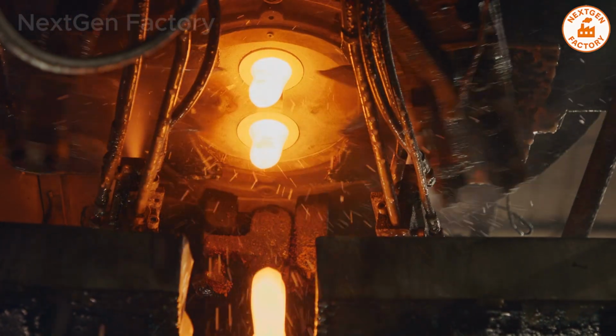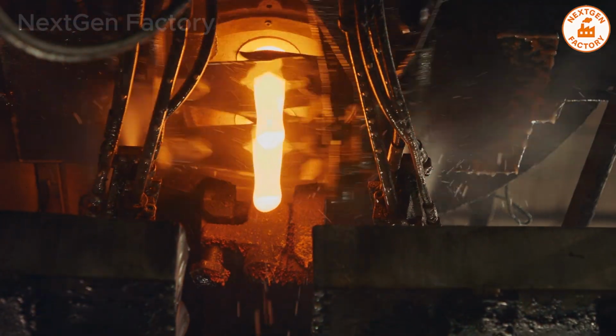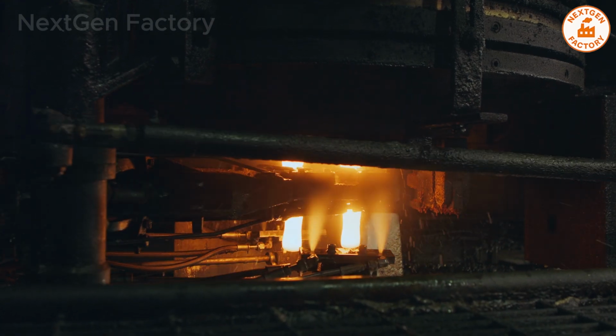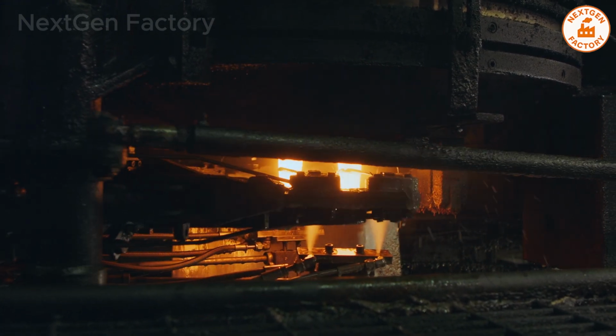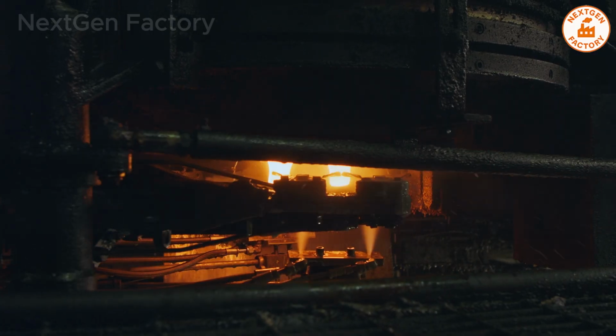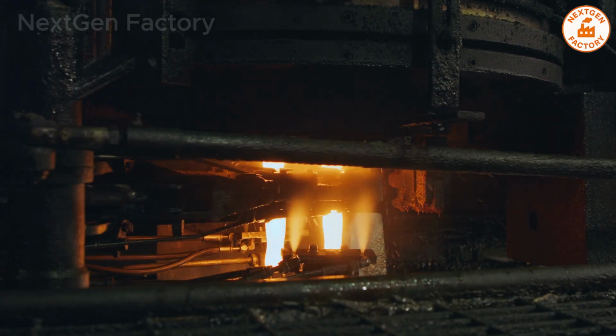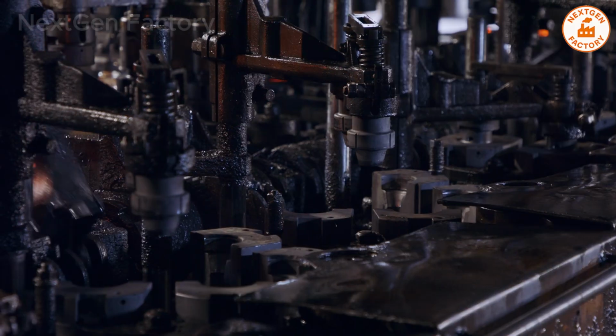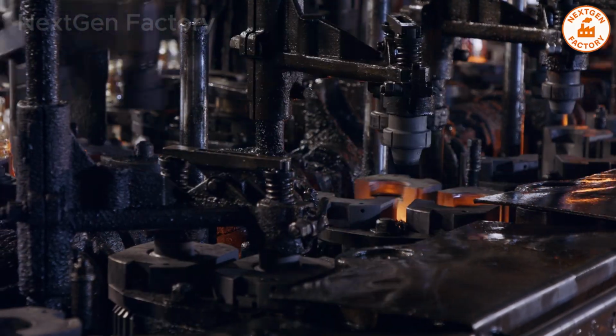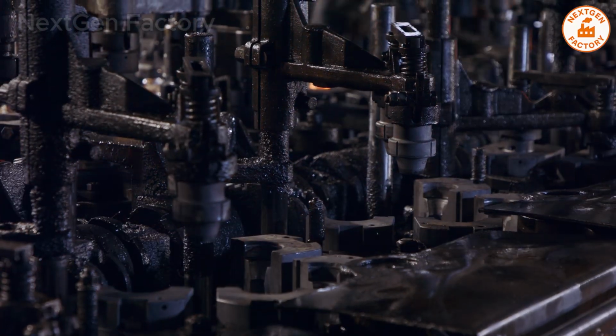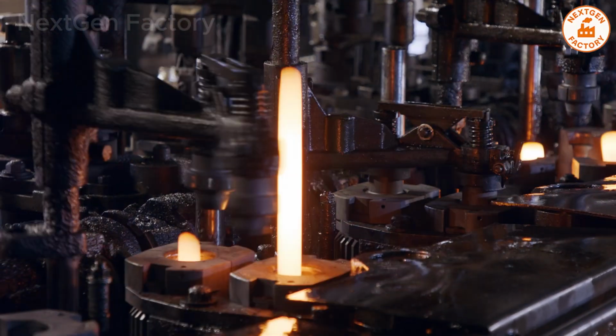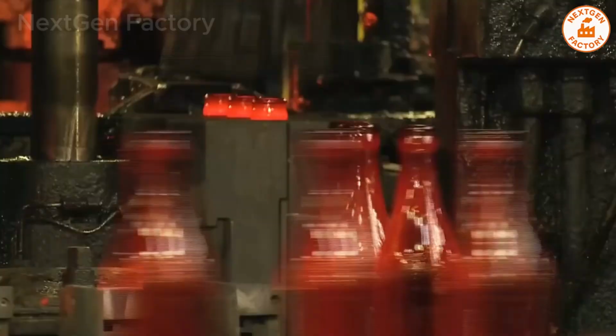Each gob is carefully weighed to match the exact size of the bottle to be formed. A gob falls into a blank mold, and compressed air blows it into a hollow preform called a parison. Robots transfer the parison into the final mold. A second burst of air expands the glass, forcing it into every contour of the mold cavity. The process happens so fast, mere seconds, that you can see hundreds of bottles forming every minute.